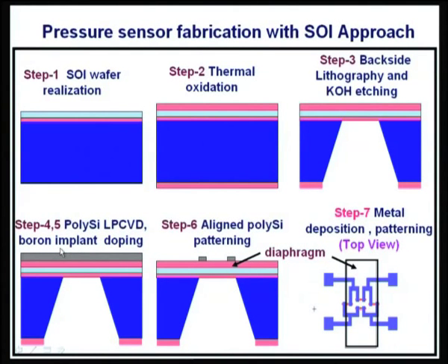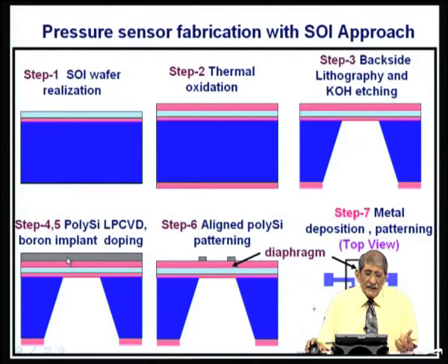So, okay, before patterning, you need to introduce boron dopant, which is p type. You introduce dopants to the extent that it brings the temperature coefficient of resistance to 0, that is about 5 x 10^19 per centimeter cubed. This doping is done by diffusion or implantation. The temperature and time of diffusion will decide that doping concentration. In implantation, the number of dopants which you have implanted will decide the number of dopants per centimeter cubed.